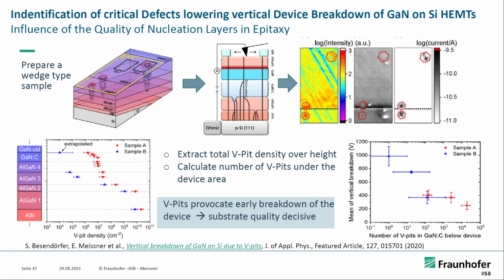What you find is that at such places, there's a special preparation you have to do. In this case, we have a wedge type sample that we produce where you can do cathodoluminescence and conductive AFM at the same place. And you see here a CL image.